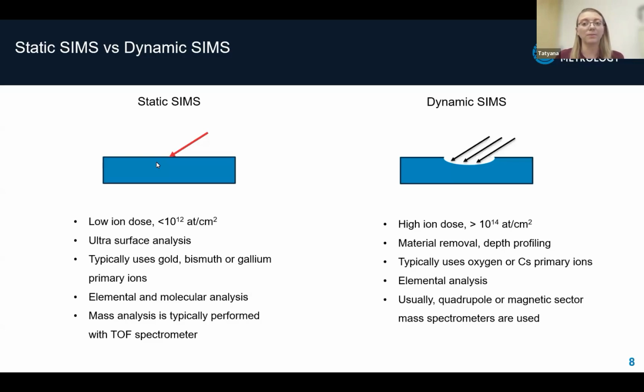Now let's compare that to dynamic SIMS. This method uses a much higher ion dose, hundreds of times more than static SIMS. It's especially useful when we need to remove material and perform depth profiling. For this, we usually use oxygen or cesium as the primary ions. Unlike static SIMS, the analysis here is done using quadrupole or magnetic sector mass spectrometers.